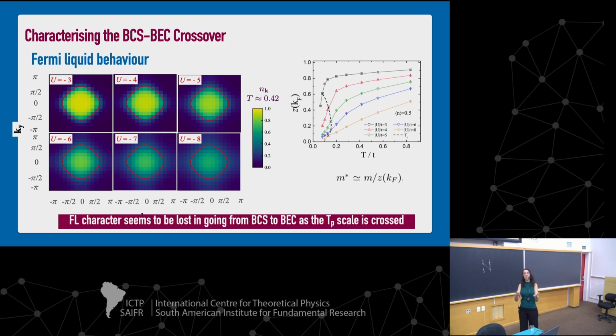One way of seeing that is, in a Fermi liquid, the Fermi sphere is easy to see. We have a clear boundary of what is occupied and what is empty. So here, this is occupied and this is empty. But as we reach this high interaction, it's kind of blurred out. And so we are losing this Fermi liquid behavior as correlations are increasing, and we are crossing over from one regime to the other.